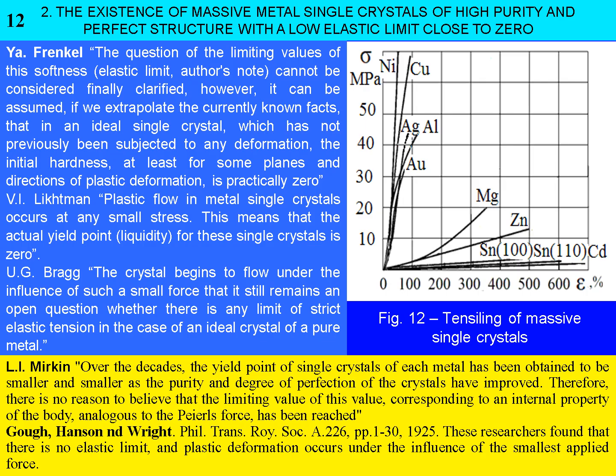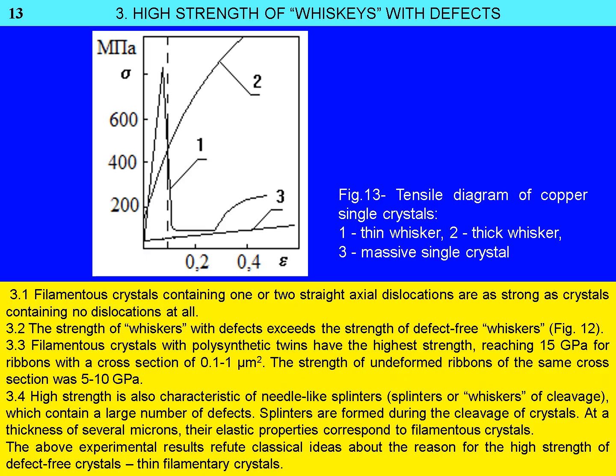This means that the true yield point of these crystals is equal to zero. Slide 12 presents additional similar quotations. The instability of massive metallic single crystals explains both their absence in nature and the difficulty of growing them in laboratory conditions. This phenomenon is not widely known, likely because it contradicts the classical concept of plasticity. Third. Slide 13, High strength of defective whiskers.